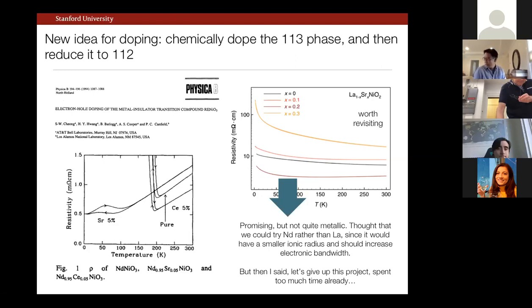And it's funny that Mark gave an extensive introduction. Indeed, at one point I was a summer intern at AT&T Bell Labs, and one of the last things I was working on before going to grad school was trying to do electron and hole doping of these perovskite nickelates. Now, many of you in the audience, or Jean-Marc's group, certainly have expertise in studying this system. It's a very fascinating system in itself, also in the perovskite phase. What you can see here, in this case for neodymium nickel O3, is a dramatic first order metal insulator transition. It's one of these very lovely canonical systems that exhibits low temperature magnetic, orbital, and correlated ordering phenomena.